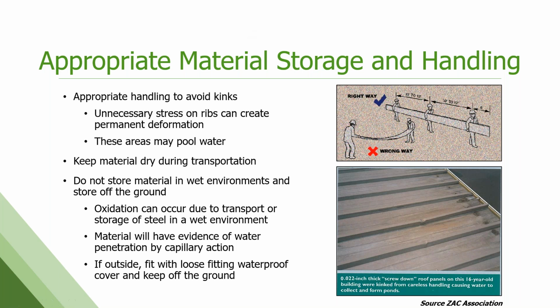Storage and handling on site is really important to metallic coated products. While this product has a superior corrosion performance once it's installed, it can be problematic when it's stored. If it's stored and stacked in bundles and moisture gets between them without any airflow, it accelerates the corrosion process. You get storage corrosion. So there's a lot of good information on how to store this at job sites so it doesn't get wet before it's installed. And then handling it, especially on long lengths, you want to make sure it's lifted up to the roof so you don't kink it or bend a panel or dent a panel, which can not only look unsightly, but can hold moisture and water and have other issues long term.